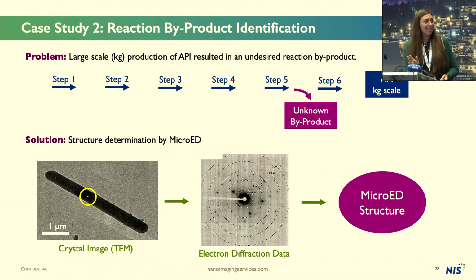So they sent it to us, and thankfully for us, it was a really ideal sample for micro-ED. They had these beautiful little needle crystals that would be too small for X-ray, but are great for us. They produce just really high quality diffraction. We got pretty lucky on that front. And we were able to determine a structure, which I can't share with you because this is pharma, but anyways, we were able to show them what it was, and now it is a known byproduct, which is great.